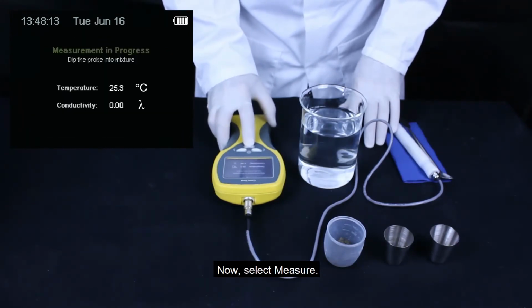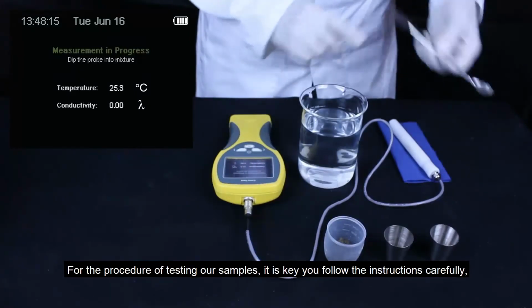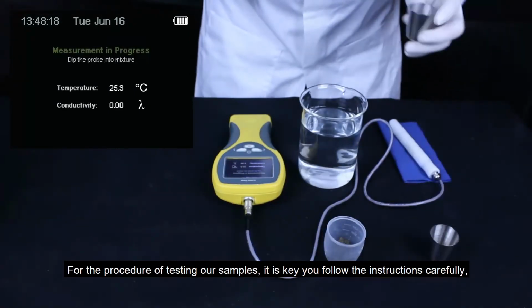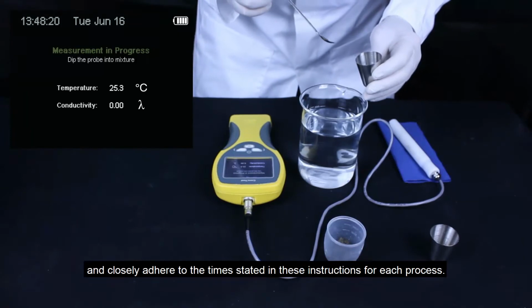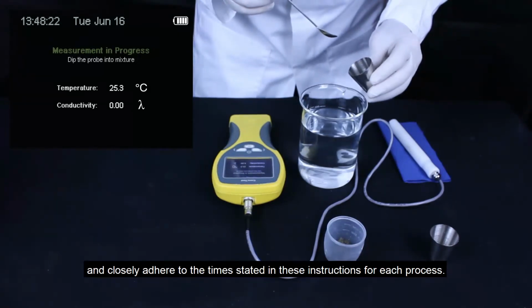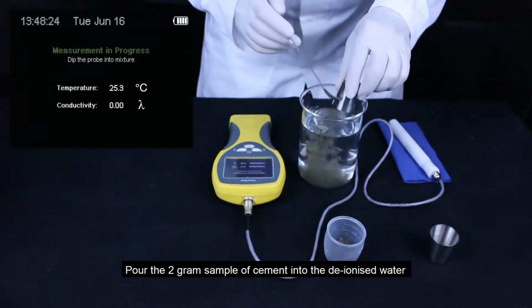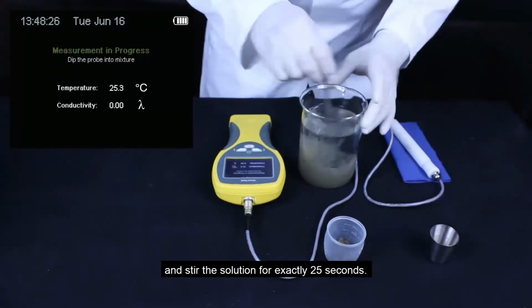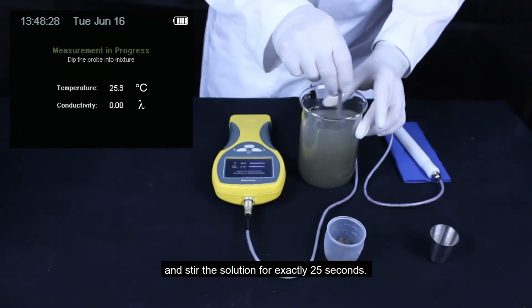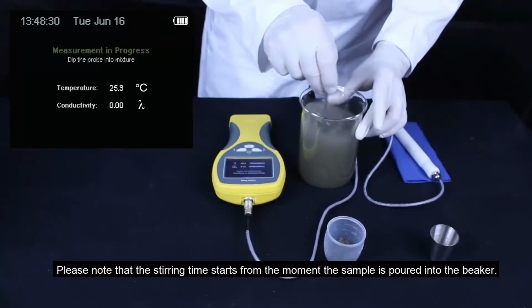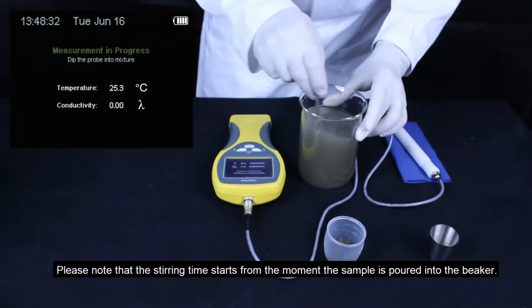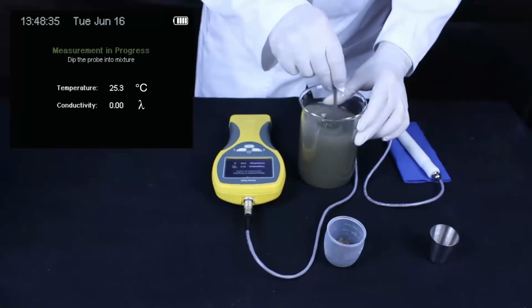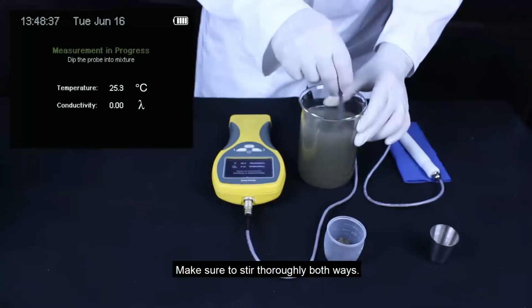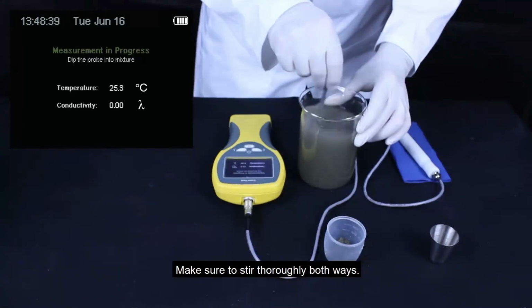Now, select Measure. For the procedure of testing our sample, it is key you will follow the instructions carefully and closely adhere to the times stated in these instructions for each process. Pour the 2 gram sample of cement into the deionized water and stir the solution for exactly 25 seconds. Please note that the stirring time starts from the moment the sample is poured into the beaker. Make sure to stir thoroughly both ways.